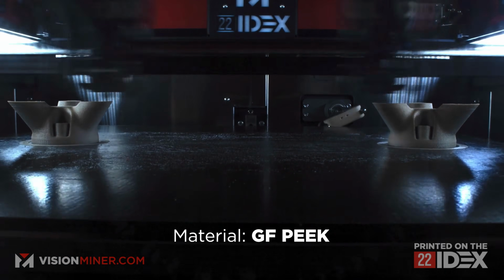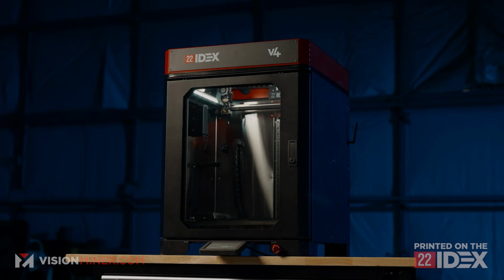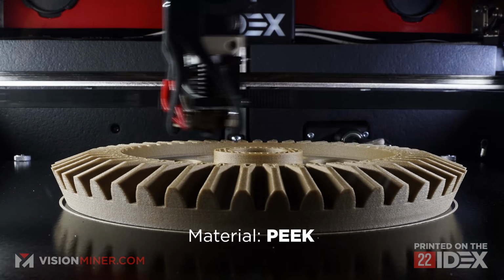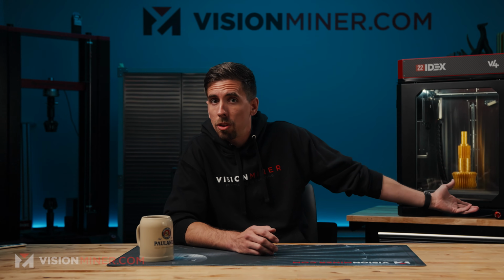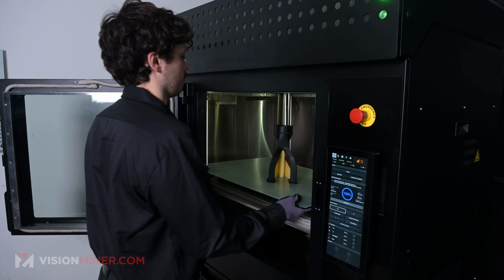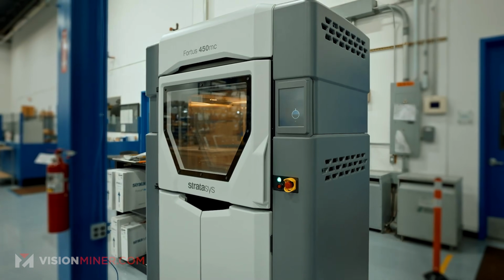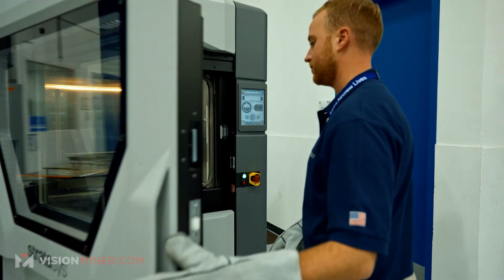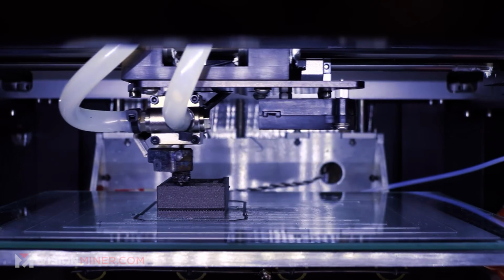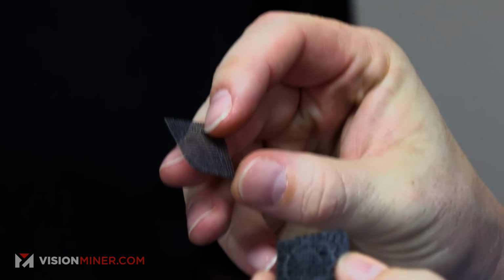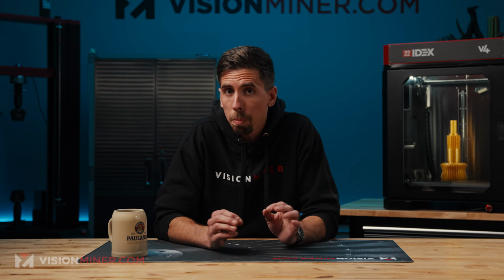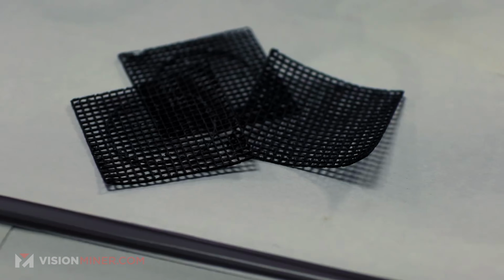So at Vision Miner, we print PEEK every single day. Our 22 IDEX was designed around the ability to print PEEK and Ultem and materials exactly like this. And for parts that are too big to fit on the 22, we even have the A3D Hilo and other large machines, which basically is an open material Stratasys 450 MC. We even did a collab video with 3D printing nerd Joel Telling just a little while back, basically a carbon fiber PEEK fuel filter for a spacewalk suit, where the tool paths inside actually made the part possible. It's the same principle that UTEP and Halliburton are using on these backup rings.